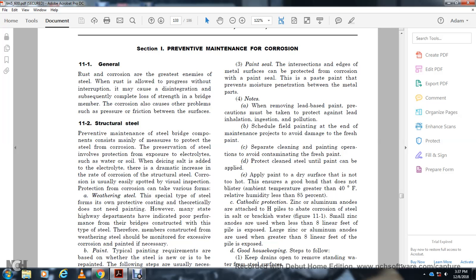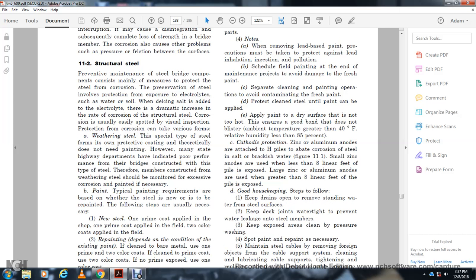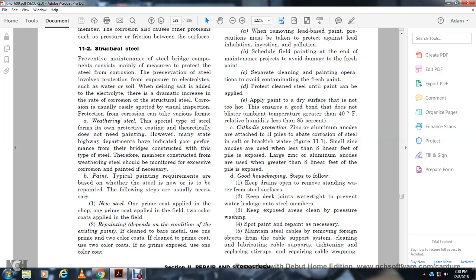Cathodic protection uses zinc and aluminum anodes to combat corrosion, particularly in salt water or brackish water environments. Small zinc anodes are used when less than 8 linear feet of piles are exposed; larger zinc or aluminum anodes are used when greater than 8 feet of pile length is exposed. Good housekeeping steps include keeping drains open, removing standing water from steel surfaces, keeping deck joints water-free, preventing water leaks down onto steel members, and keeping exposed areas clean.